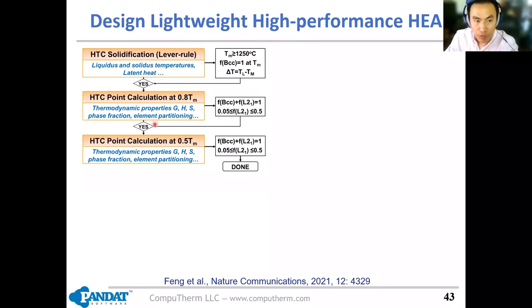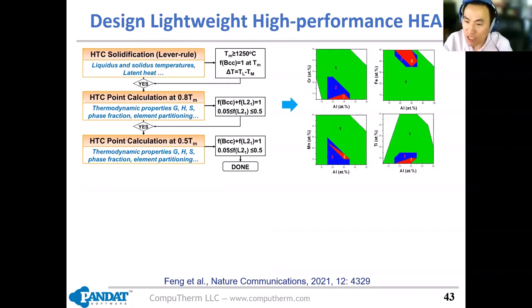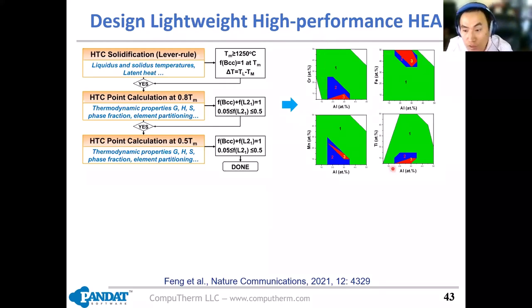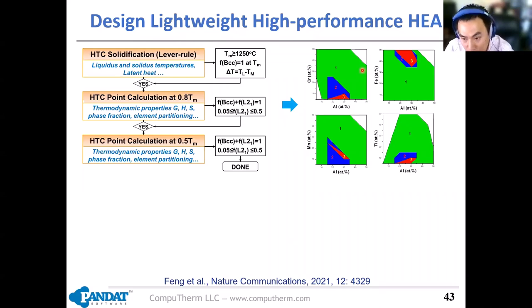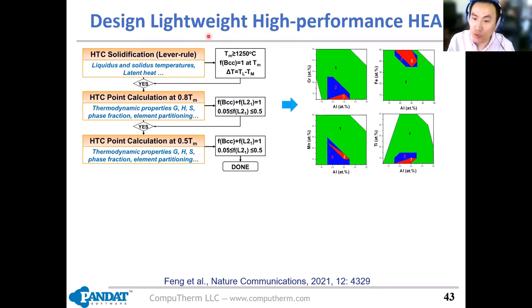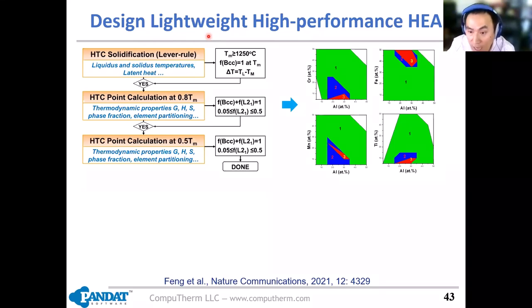This flow chart shows the high-throughput calculation steps and screening criteria. For high-temperature application, we require the melting temperature to be greater than 1250°C. For precipitation strengthening with L21 precipitates in the BCC matrix, we need identified alloys to have a single BCC phase at high temperature, and only BCC and L21 phases at low temperature without forming other detrimental intermetallic phases. Based on these criteria, we performed three rounds of high-throughput calculations. The figures show the composition distribution of identified alloys at each step — the x-axis is aluminum composition and the y-axis is the composition of the other four elements. Green area 1 meets criterion 1, blue area 2 meets criteria 1 and 2, and red area 3 meets all three criteria. Finally, eight alloys were screened out of more than 3,000 alloys and experimentally investigated.